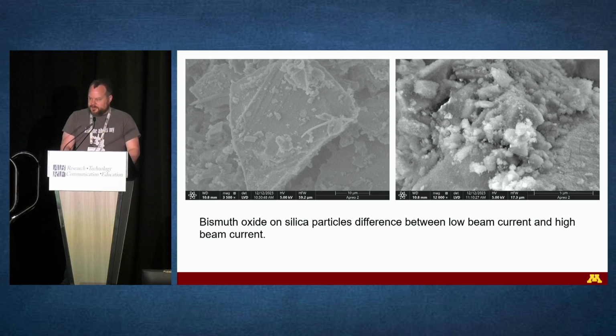More of the work I do is in the materials side, though, and so here we got bismuth oxide on silica particles. This is a catalyst being investigated, and depending on the beam conditions, you get a very different view. So on the left, we have a picture that is at low beam power, low beam current, and we get a lot of secondary electrons.